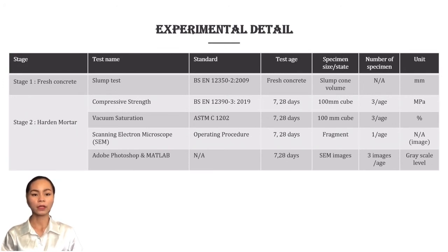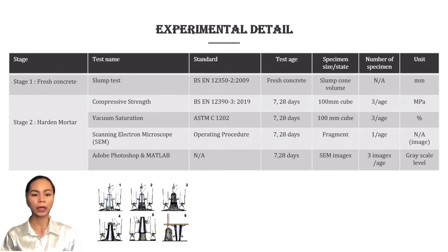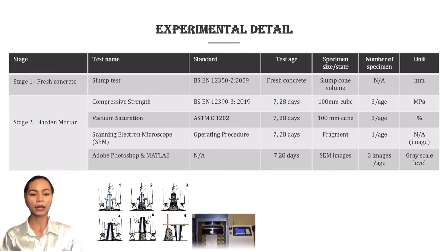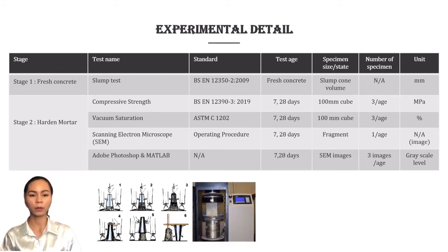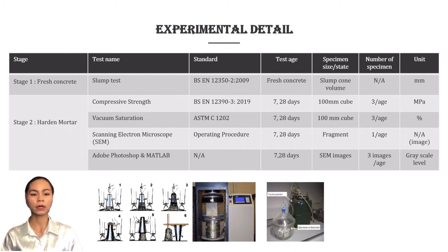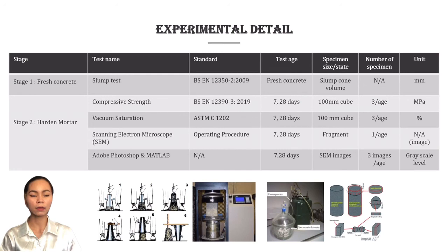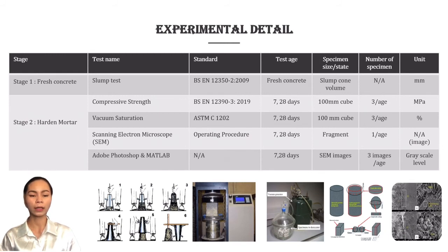In stage 1, which is fresh concrete, the slump test is done before the concrete paste is poured into the cube mold. Next, for the second stage, the compressive strength test needs to be done to achieve the concrete grade used in this study. After the concrete passes the required strength, vacuum saturation and scanning electron microscope take place. The SEM images of concrete are next analyzed using Adobe Photoshop software first to determine the grayscale threshold, and MATLAB is used to quantify the porosity of concrete.